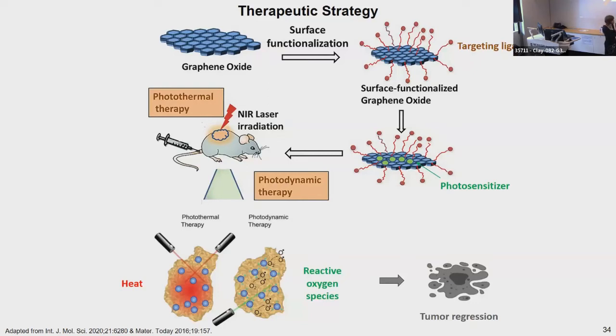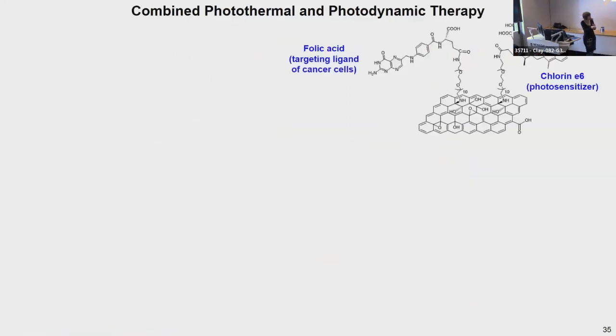The idea also was to exploit the photothermal capacity of graphene oxide, because graphene oxide under irradiation with near-infrared light can absorb the light energy and convert it into heat. And this can be used to treat tumors. So we wanted to combine both therapies, photothermal therapy and photodynamic therapy, to treat cancer cells. So we prepared this double functionalized graphene oxide.